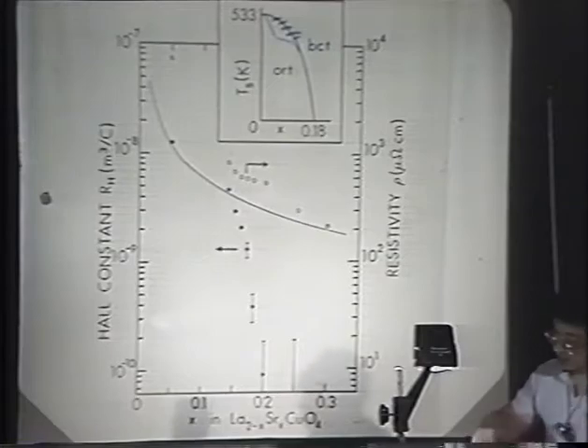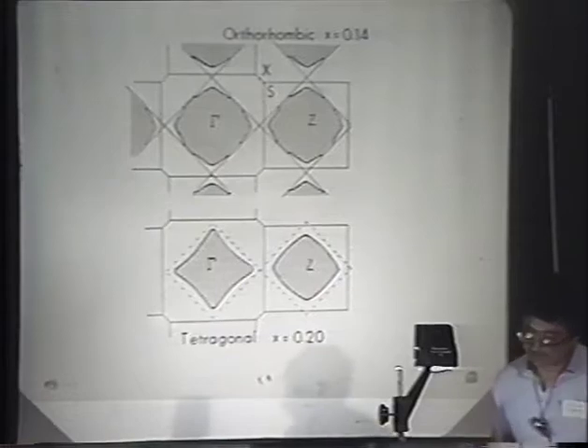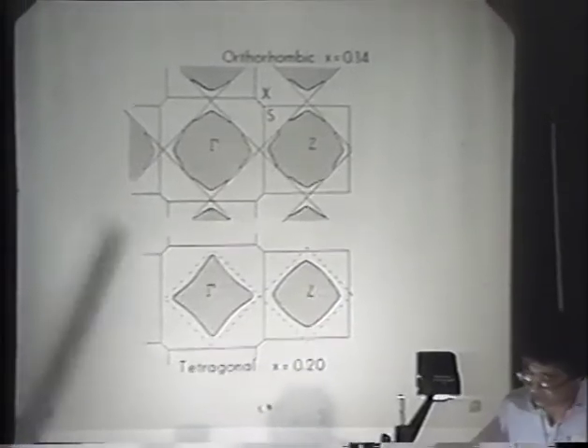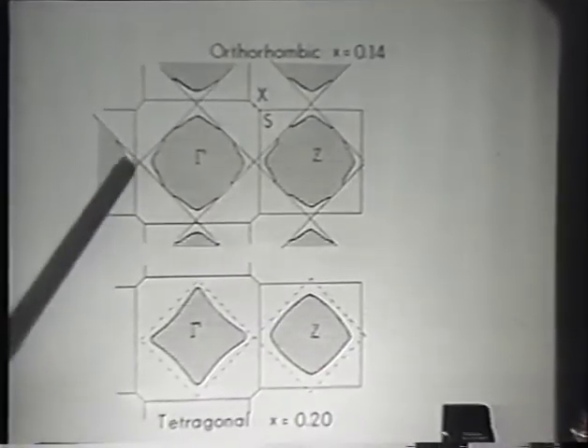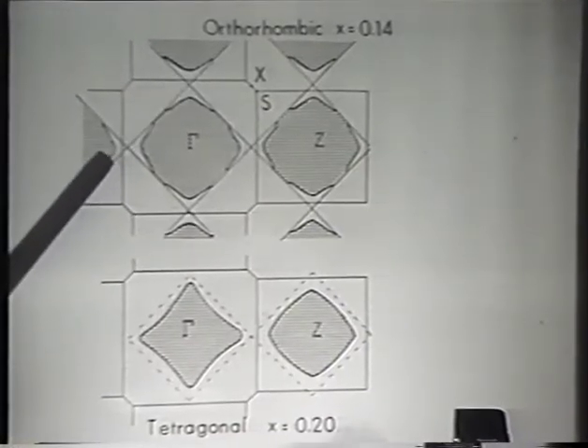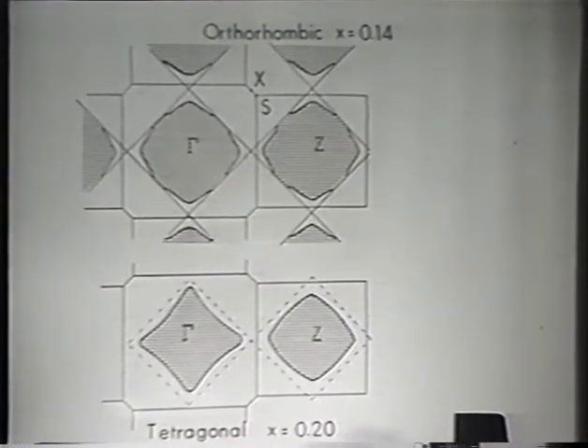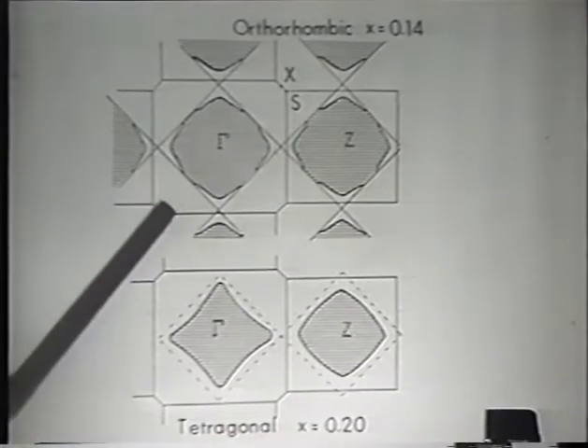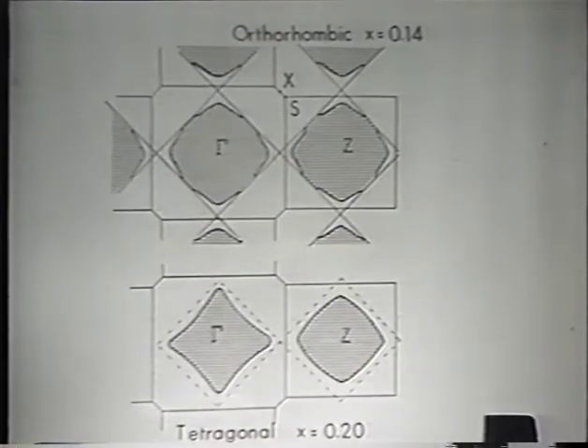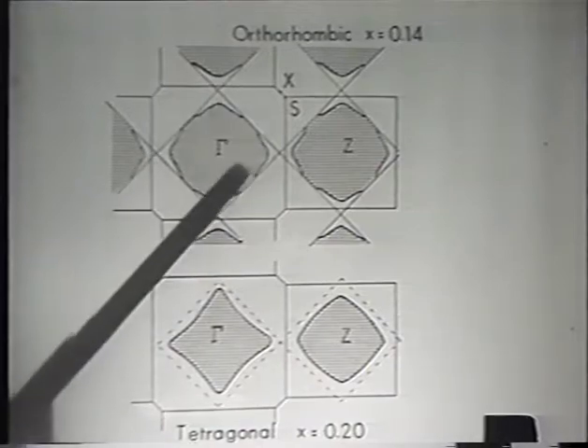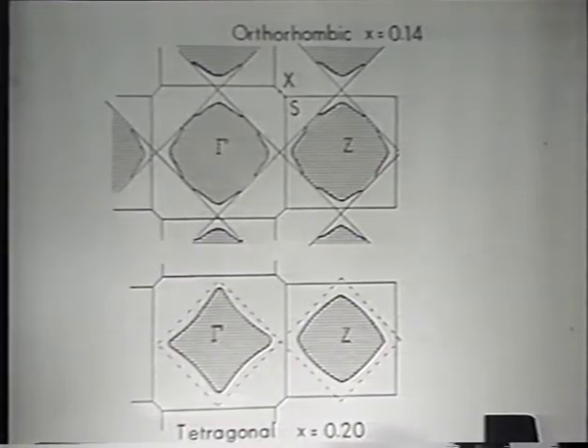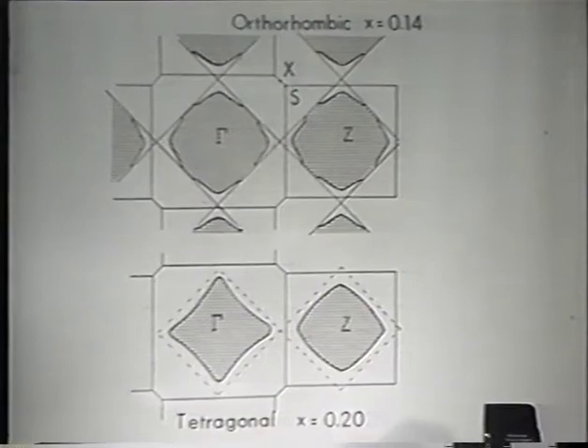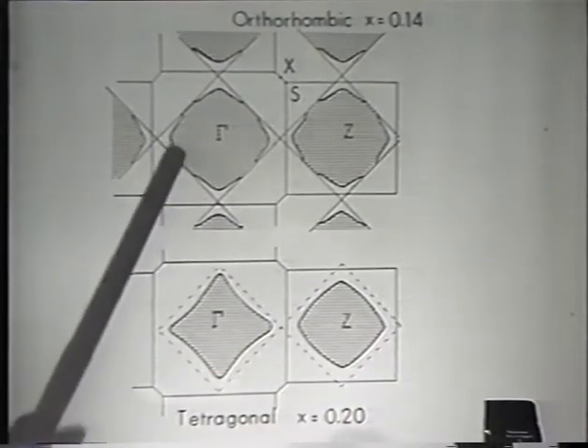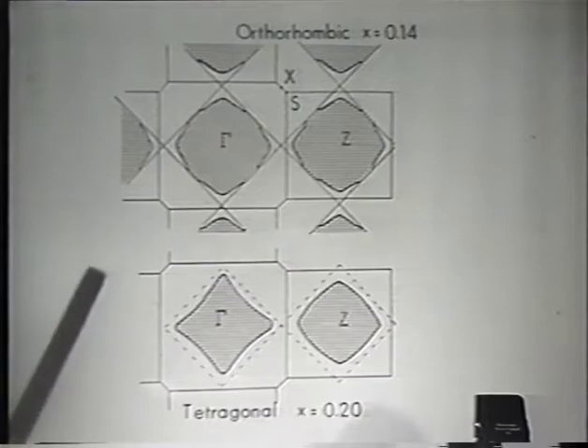We have a simple model which accounts for most of these features, and let me just go through it. In the orthorhombic phase, we assume that there's a gap in a 110 direction. Just let me have that gap. In the x equals 0 compound, there's a complete filling of this first Brillouin zone, and so it's semiconducting-like. Now, the key point here is that when you dope it, you open up a pocket here, but the gap has to stay at the same place.